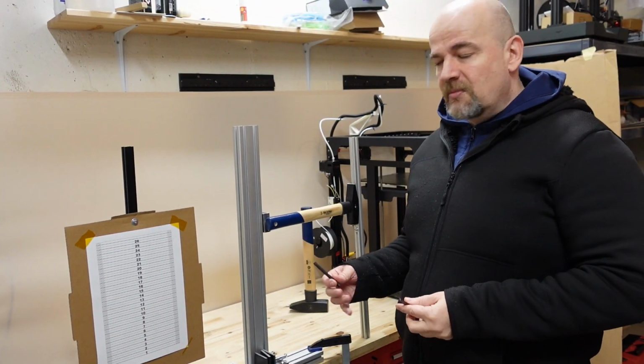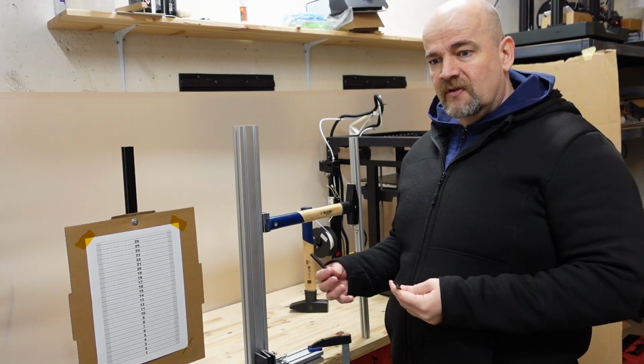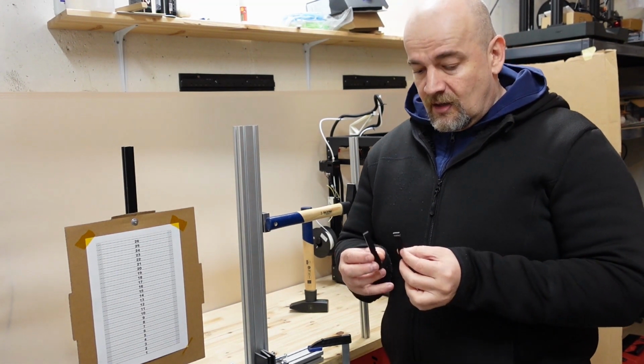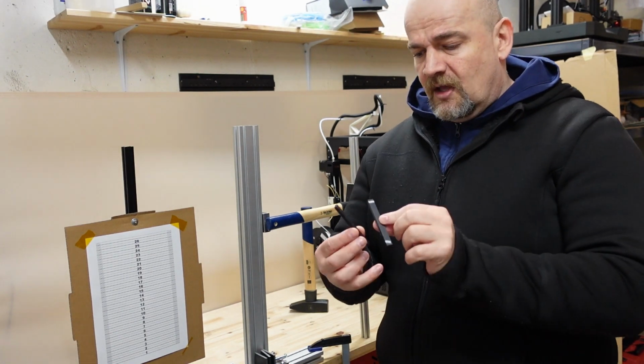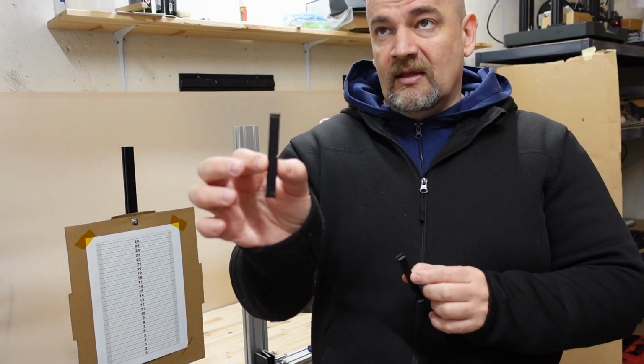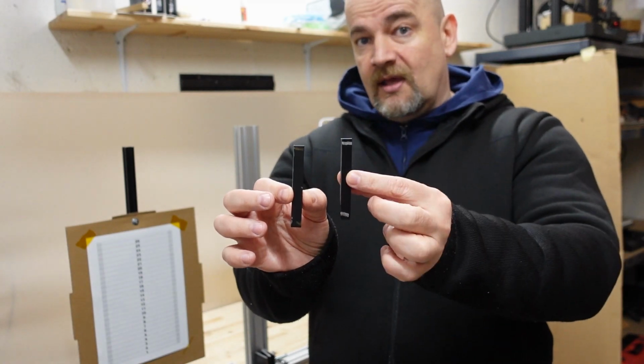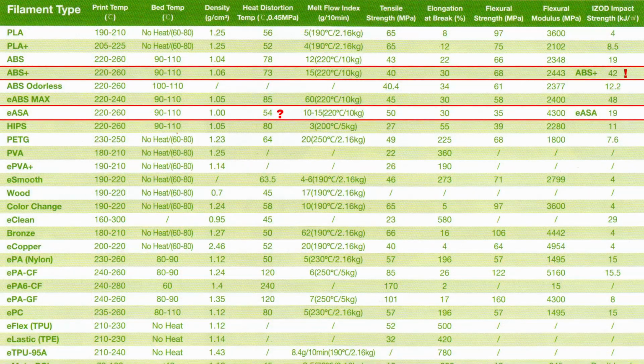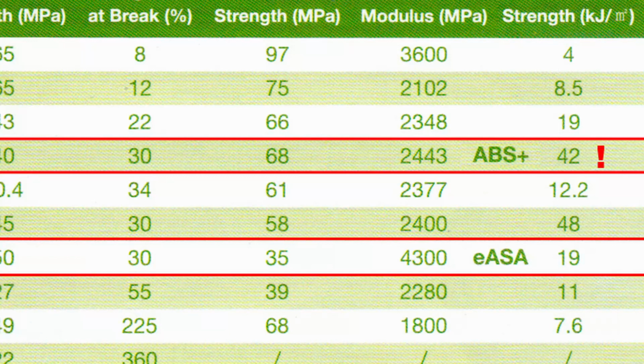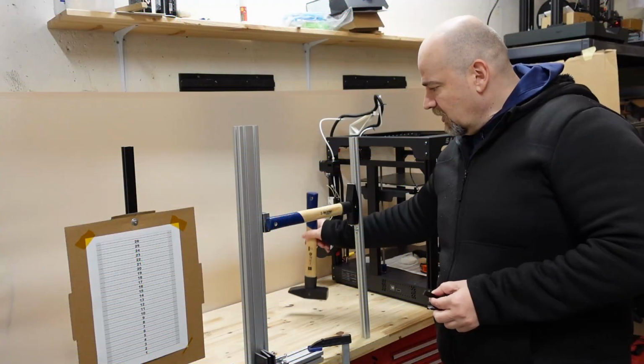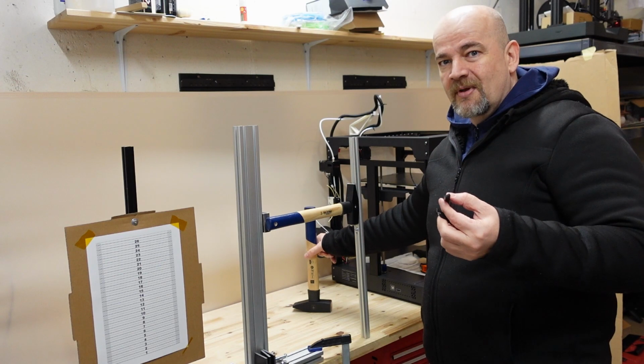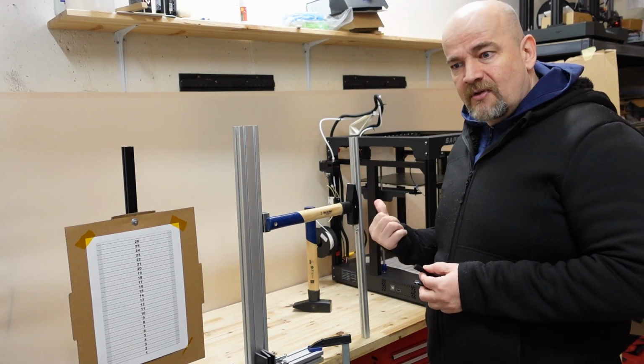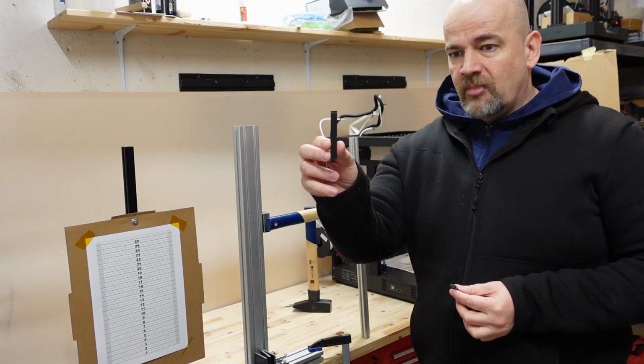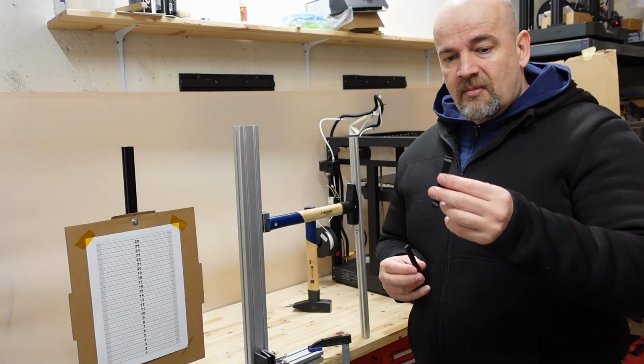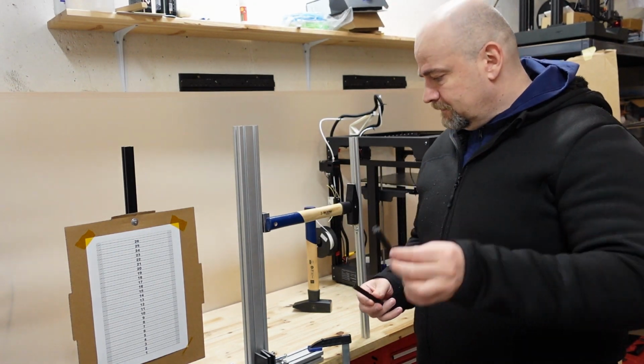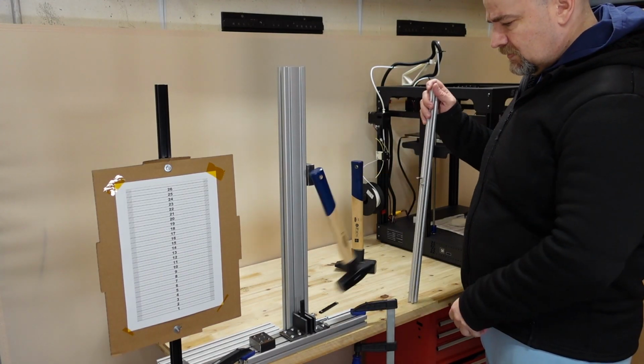And it's time for the Izod impact test, and here I'm expecting some of the biggest differences between these two materials. According to manufacturer specifications, the ABS Plus has at least twice the strength of the ASA. And actually this was the only test specimen which didn't break under the half kilogram hammer. I have a 1 kilogram hammer too, but I got some skeptical comments, so I decided to use a half kilogram hammer. So I'm expecting that it will not break the ABS Plus test specimen, and I'm curious what will happen with ASA. ABS Plus.